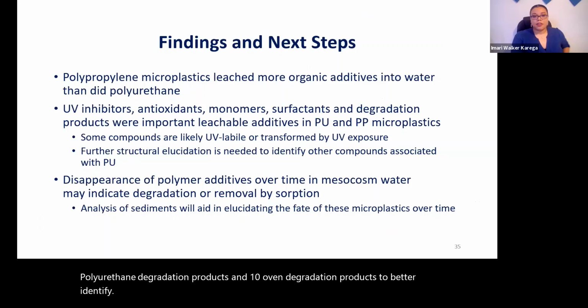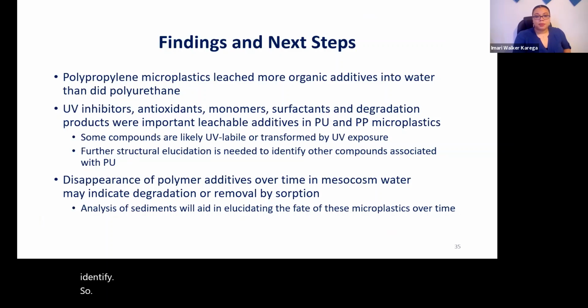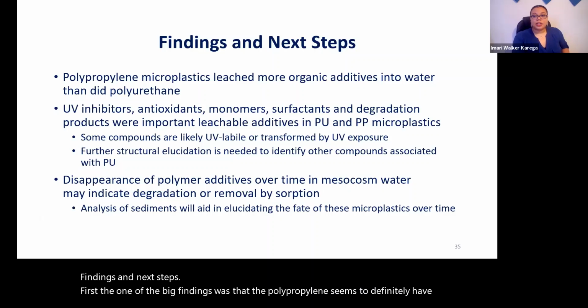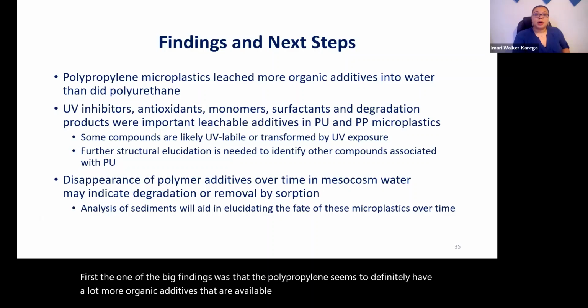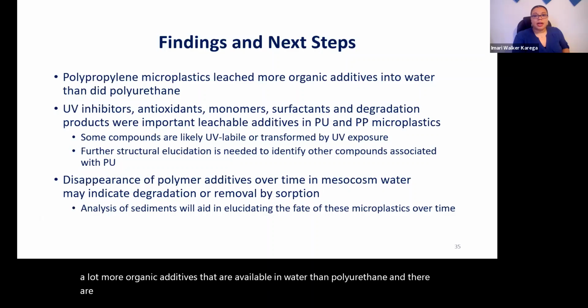So, findings and next steps. First, one of the big findings was that polypropylene seems to definitely have a lot more organic additives available in water than polyurethane. There are multiple different types of polymer additives found within both polypropylene and polyurethane.